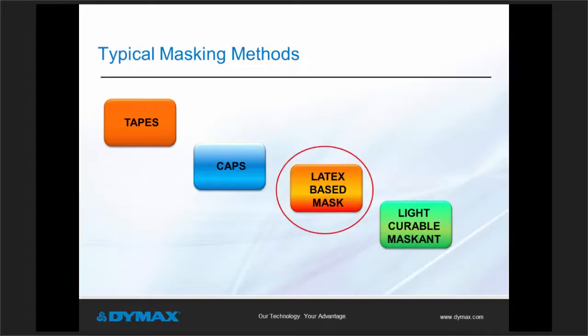Latex-based maskants are yet another option for protecting your connectors and the board surfaces. Latex-based maskants are 50% solids, so you'll need to flash off the solvent or heat cure, or air dry the maskant. The curing times range from 15 minutes for heat up to 8 hours if you're air drying the maskant. Depending on the viscosity of the maskant, multiple applications and multiple cure cycles are required to achieve the full protection coverage. Some of the latex-based maskants have an ammonia content, and that may cause discoloration or corrosion of the pins.